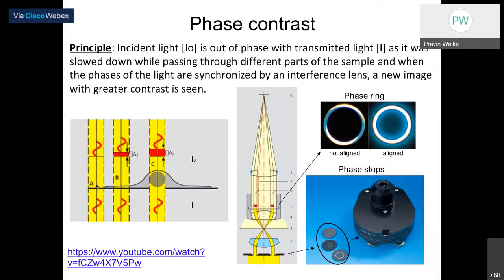So what happens if we slowly move this light or scan this light over the different parts of the sample? What we observe is that the phase of the light needs to be synchronized with the interference lens to get a highly contrasted image. For example, here you see that particular interference lens has been added, and these are the different lenses which have to be added in between the column. And then once it's synchronized by the interference lenses, we can find this phase ring.